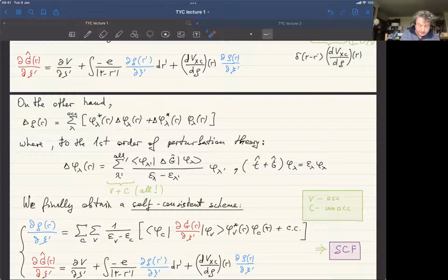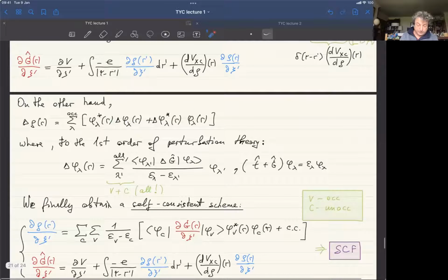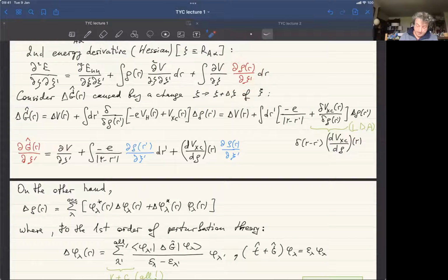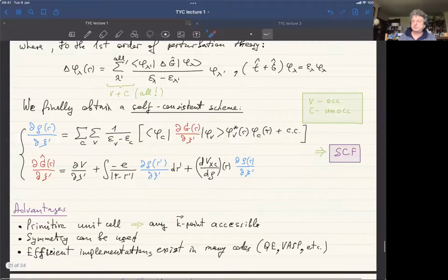Right. From that, if you divide this by delta Xi, you will have the derivative of the Kohn-Sham orbitals, and you arrive at a set of two equations to determine this derivative. So that derivative, which we require for calculating the force, can actually be obtained from here. So that's the idea. You see these are coupled equations which are solved in practice using some kind of self-consistent procedure, but it gives access to the change of the orbitals and therefore to the change of the Kohn-Sham potential and therefore to the forces on atoms.